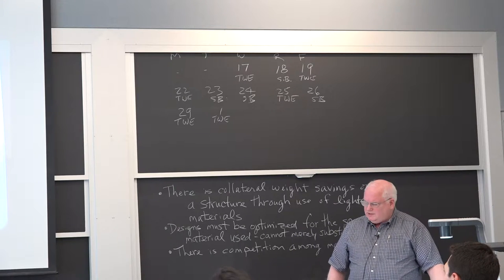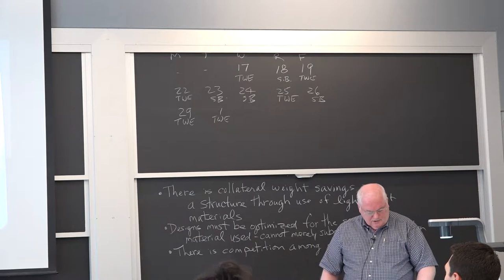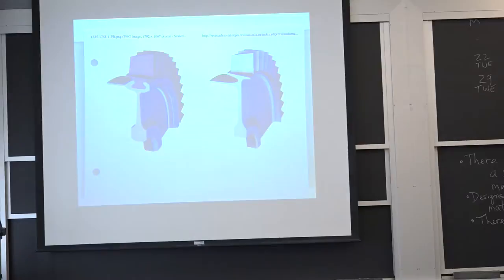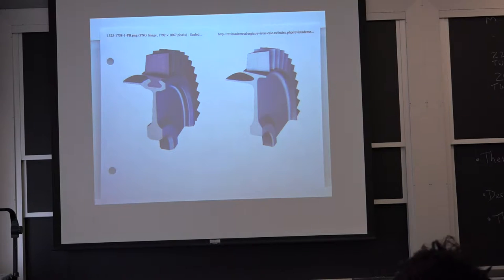I should have looked for Blisk on the web. Here's one I did this morning, and the web's getting better and better. This is a nice graphic of a turbine disk that is not a Blisk, and here's your root where the vane has to attach to this big heavy flange, whereas over here you can make the whole thing integral, which they do for 30,000 M250 engines of Rolls-Royce. This thing is a lot lighter than this great big mass right here, as you can see. Okay, so you'd like to do that because there's collateral weight savings.